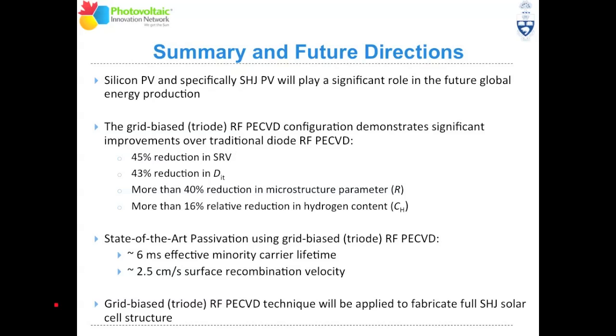So just to summarize, silicon PV, and specifically the silicon heterojunction PV cell, will play a significant role in future global energy production. The grid-biased triode configuration demonstrates significant improvements over traditional diode RF PECVD, where we've demonstrated a 45% reduction in surface recombination velocity, a 43% reduction in the interface defect density, more than a 40% reduction in microstructure parameter, and more than 16% reduction in the hydrogen content. We also achieved state-of-the-art passivation.